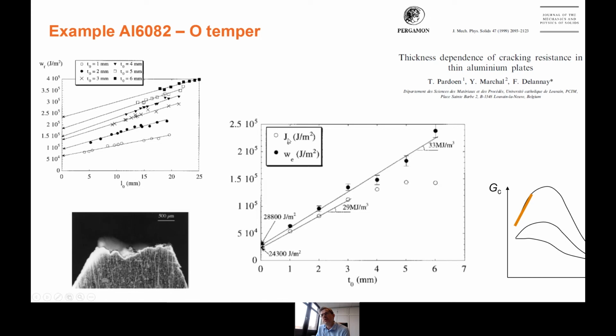The JIc or Jc, we should call it JC because we are not in the plane strain regime. You see it's smaller than the essential work of fracture and gets smaller and smaller, and JC reaches a plateau. So we are near the top of the curve, but we could not get points. We worked with a 6mm sheet at that time, and so we have no data for the unloading.